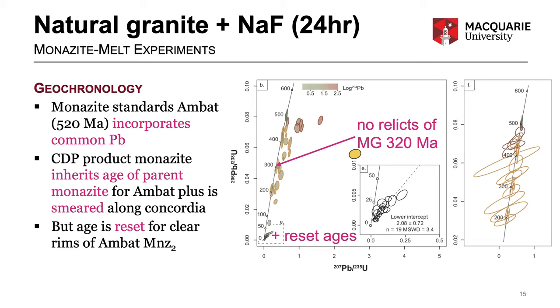They still have some history of that precursor uranium-lead isotopic story in them, or in the ablation volume. The analyses of the other domains, T1 to T3, spread out along Concordia over 200 or 300 million years. This pattern formed in a day, and those ages are not really geologically significant individually.